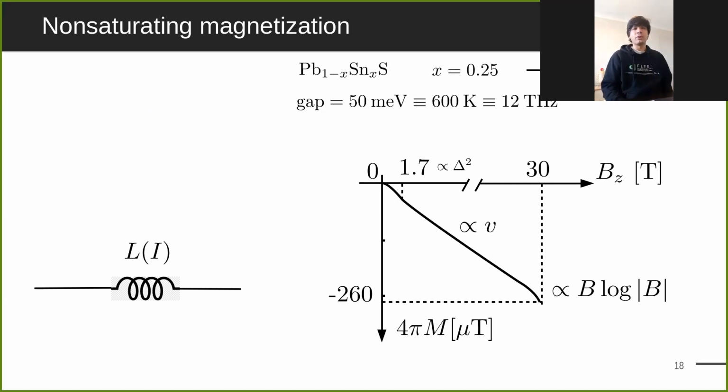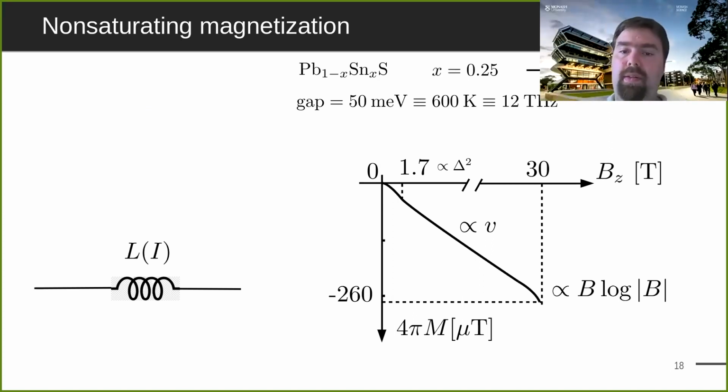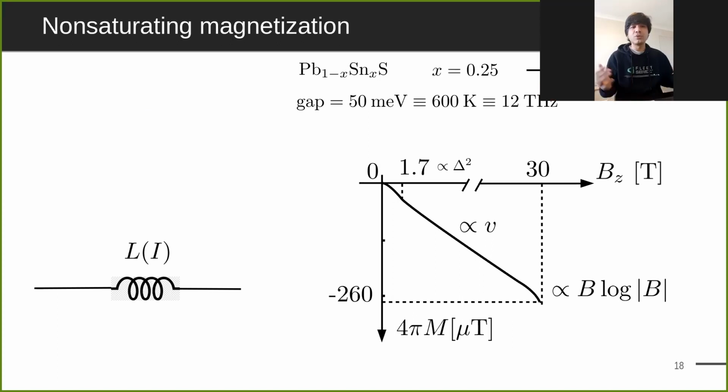In a Dirac system, though, there's nothing in the conduction band. Everything comes from the valence band. And the valence band has quite a large cutoff, like 1 or 2 electron volts. So unless you go to extremely large magnetic field, I don't know, some 50, 60, 100 Tesla, you can never isolate that lowest Landau level. It always comes with other Landau levels in the valence band. What you see here is the aggregate effect of those Landau levels, not due to one lowest Landau level, but the summation of energy of low Landau levels in the valence band that has a logarithmic contribution to susceptibility.